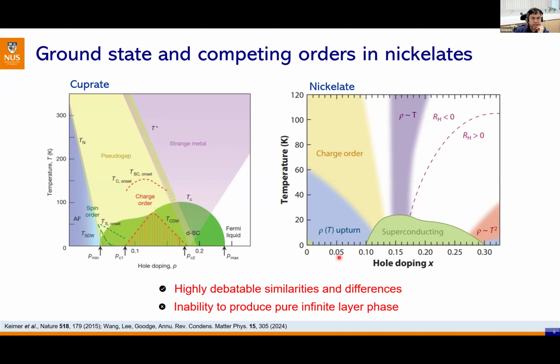So there is the appearance of RP phase and secondary phase defects, even during the initial growth of the perovskite, and worse when we are doing the oxygen reduction by calcium hydride, for example. There have also been many other effects: formation of defects on the surface, absorption of oxygen, formation of other secondary phases, or even the intercalation of hydrogen.